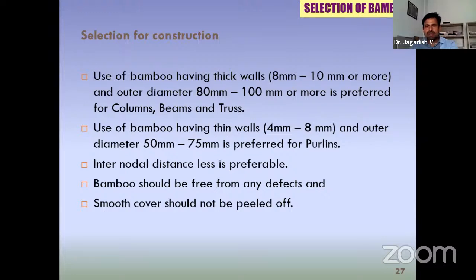When you cut at the bottom, it has more diameter, and when it goes to the top portion of the bamboo, it decreases, so it tapers. So you have to make sure that on the minimum diameter side, you should have a minimum 10 mm wall thickness. Wall thickness is nothing but outside diameter minus inside diameter.